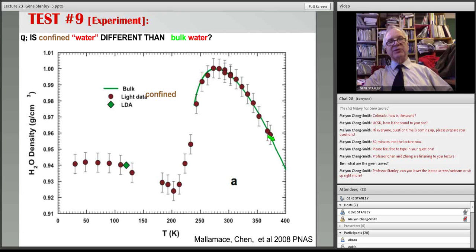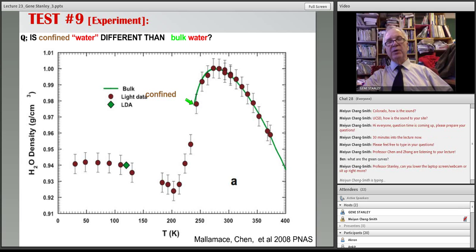And the red circles are the actual measurements on confined water. And as you see, first of all, they agree with the bulk water, as they better, but they might not have to. They agree with the bulk water, but unlike the bulk water, they don't stop at about minus 35 or so, where the bulk water stops, but they just keep on going down, down, down. There's actually a density minimum, which the Chen and Mallamace groups discovered for the first time in water way down below the hypothesized critical point, after which the density becomes more or less like a normal material. So as regards this property, confined water is the same as bulk water.